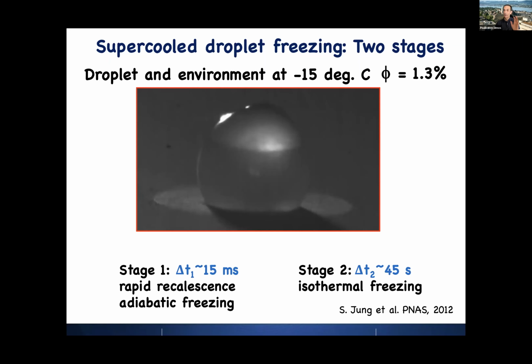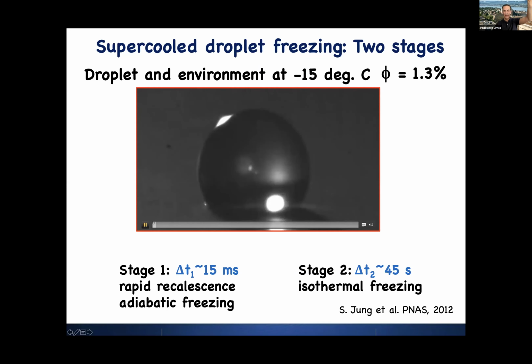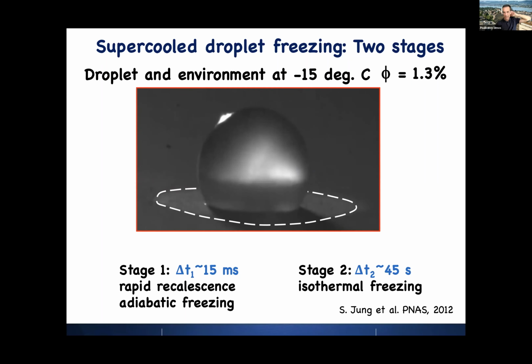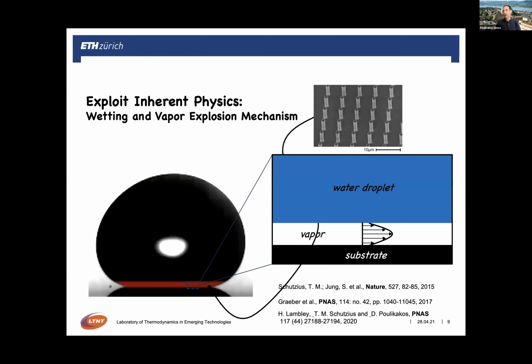Now, with that, of course, the following comes, that the droplet, like I said, finds itself to be very hot suddenly in a cold environment and then vaporizes. So there's a vapor explosion taking place, which you cannot see here, unfortunately. But what you can see, its manifestation a little bit, because some of this vapor will condense around the surface, and you will see, if you look carefully here, that this surface will be surrounded by what I call a condensate halo.